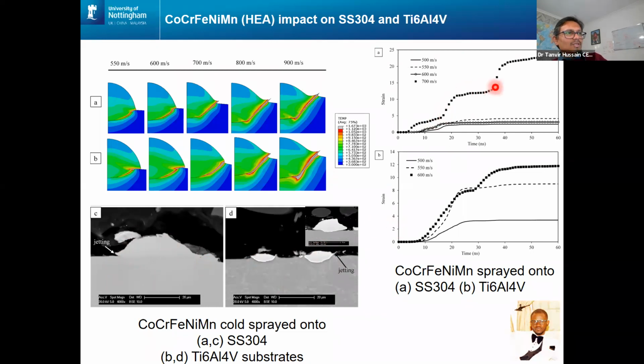And what happens in cold spray is the thermal softening dominates over strain hardening, and we can see a jump in strain. And by looking at which point the strain jumps, you can figure out what's the critical velocity required for particles to deposit to form bonding. So there is no melting taking place. All we are working with here is the velocity or the momentum of the particle.